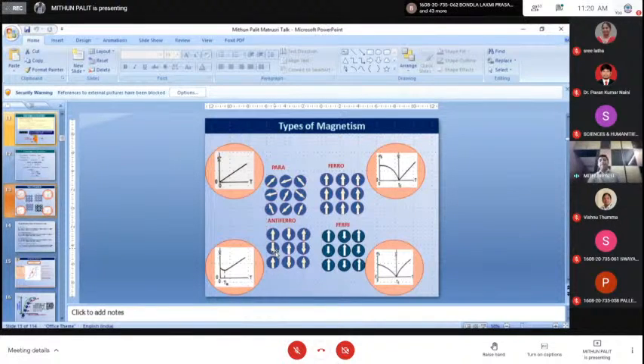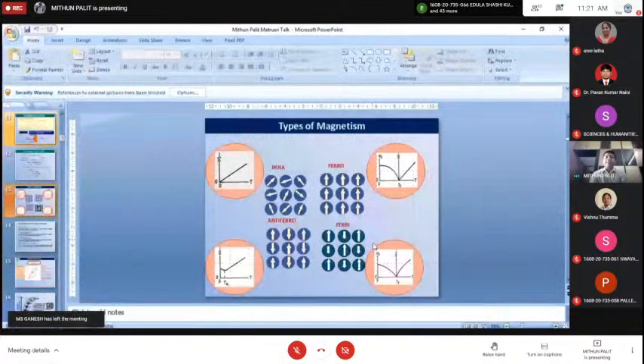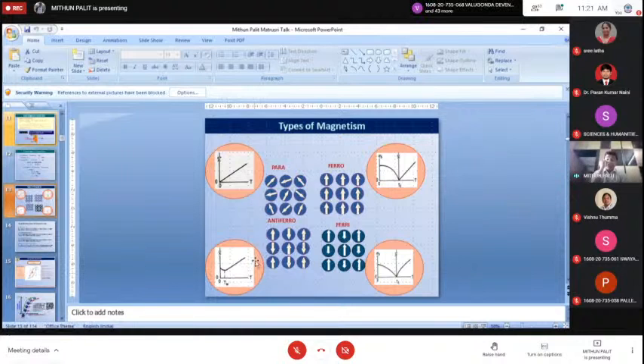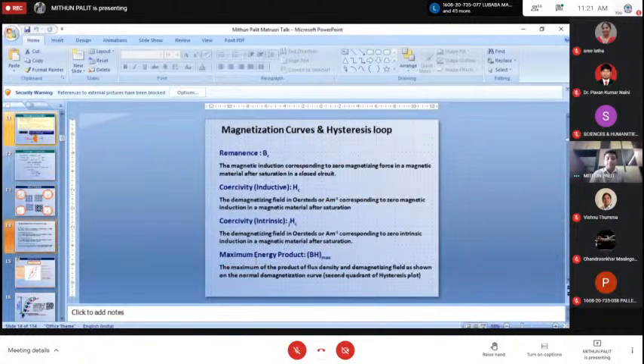is called antiferromagnetic material. And in antiferromagnetic material, sometimes one lattice's spins do not completely neutralize the other lattice's spins, and those materials will have a weak magnetism at room temperature, so they are called ferrimagnets. And antiferromagnetic materials also undergo ordering. This kind of perfect ordering of the two spins in opposite directions happens at a temperature below what is called the Néel temperature, and beyond this Néel temperature they again become haphazardly oriented like a paramagnetic material.